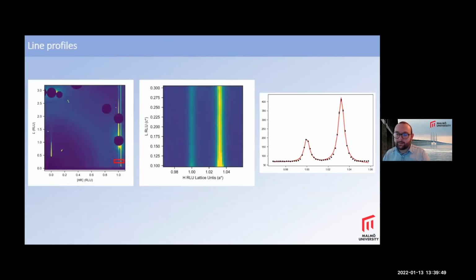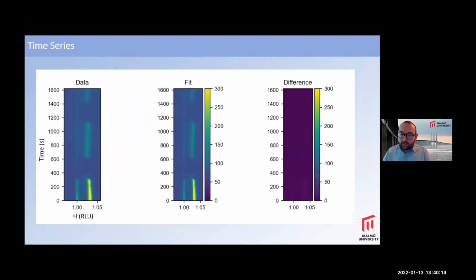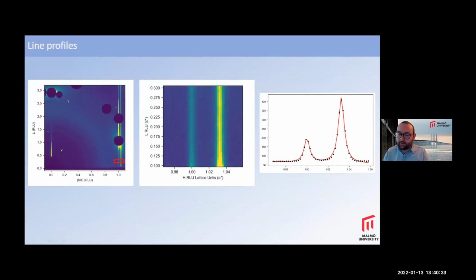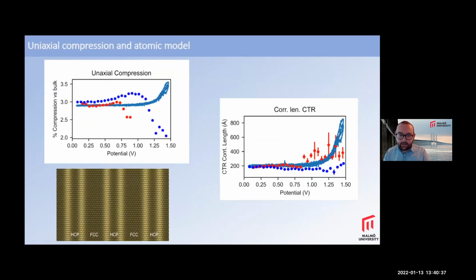Okay, we can also analyze it in a more sort of conventional way. So we can take a line profile almost through the CTR and the reconstruction. If we add it to get sort of a better signal, and then we can plot that and fit a double Lorentzian, and this has been done in the past quite successfully. We can look at our fits as a function of time. So this is the data. This is the fit, so it matches pretty well. And this is the difference. So there's not very much deviation between our fit to this line profile and actually what we see. And from that we can extract various parameters about our electrode surface.